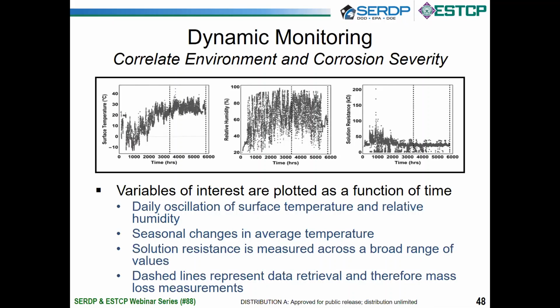On the rightmost curve, you can see the solution resistance data, and you can see there's a very distinct regime of where we have high solution resistances or low solution resistances. High solution resistances would correspond to events that are dry, where there is no presence of a conductive electrolyte. And so we'd expect those data points to be very low in corrosion severity, whereas the wet data points correspond to the presence of conductive electrolyte and therefore are corrosion prone events. Slide 49, please.